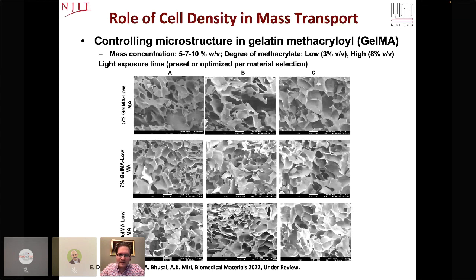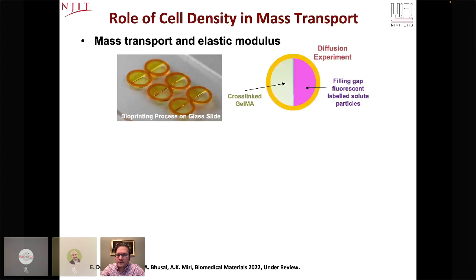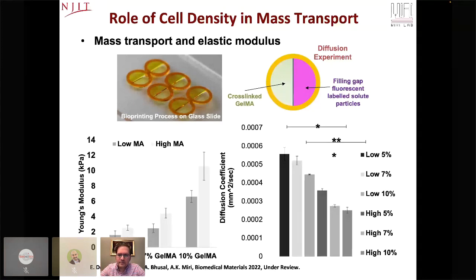One of the questions is how we can control maybe the mass transport properties even as a function of cell density. When you are playing with bioink, you can control the mass concentration from, in this case, we chose 5%, 7%, and 10%. But for those 3, we can also play with the degree of methacrylation or the degree of photocrosslinking from very low to high. And also we can keep the exposure time as a fixed number, an optimized number that we can continue with for the rest. And now we're going to see how the mass concentration and cell density are affecting our mass transport properties, our biotransport properties. And we try to test this by a simple standard experiment in our lab to see if we can fabricate the particle-filled gel on one side, and the other side would be with no particle. We can see the mass transport in different cases.